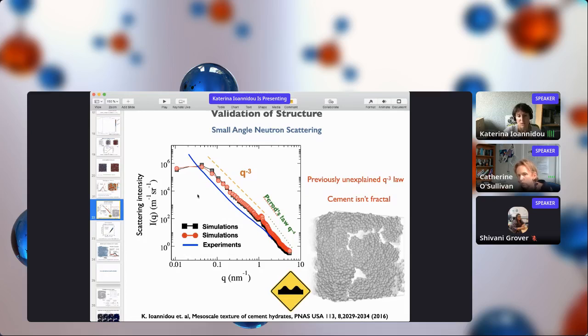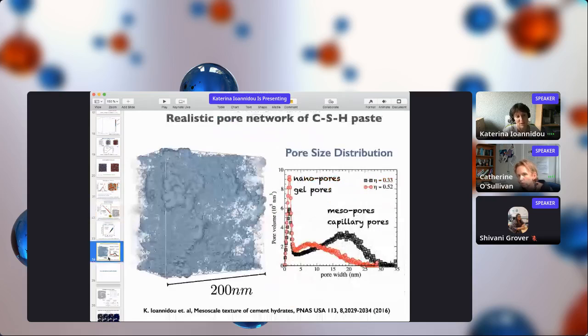If the system is homogeneous and has a well-defined representative volume element, we can stay with a small system. But when we talk about systems that have such large heterogeneities, both in the scattering and in pore size distributions, in order to find pores that are so large, we need to go to system sizes that are at least 200 or 500 nanometers, starting with particles which are only 5 nanometers.